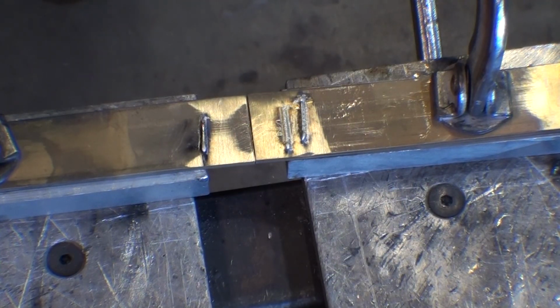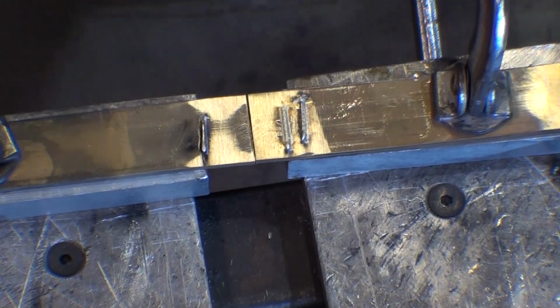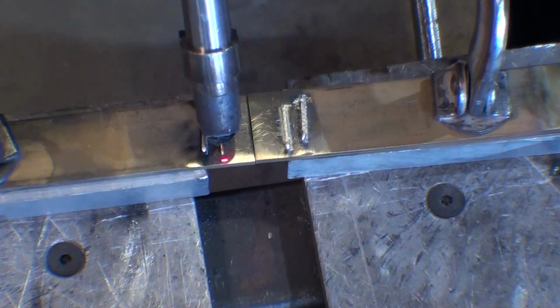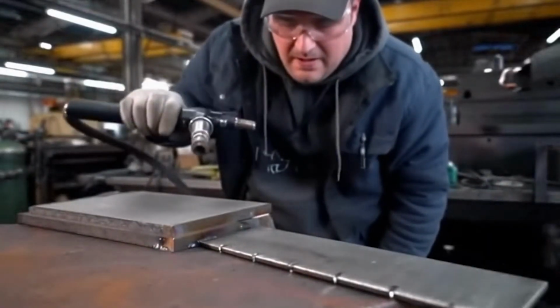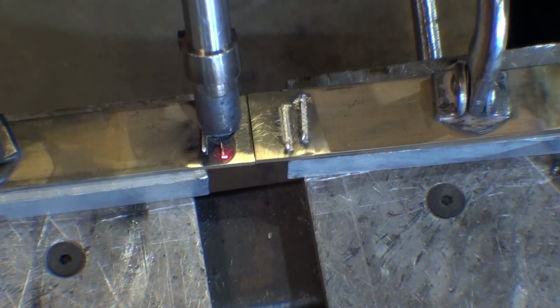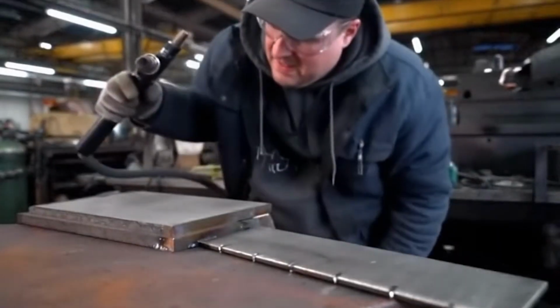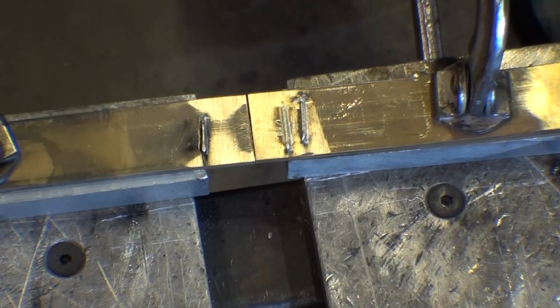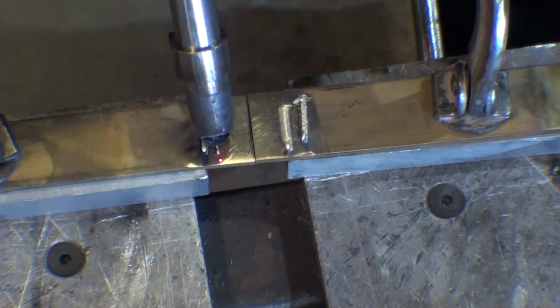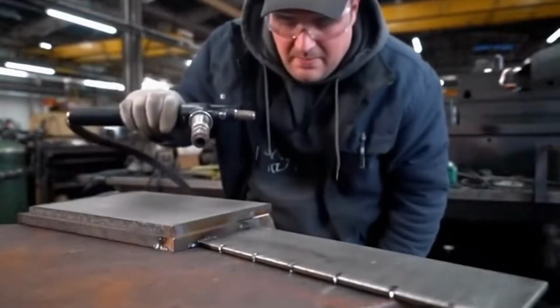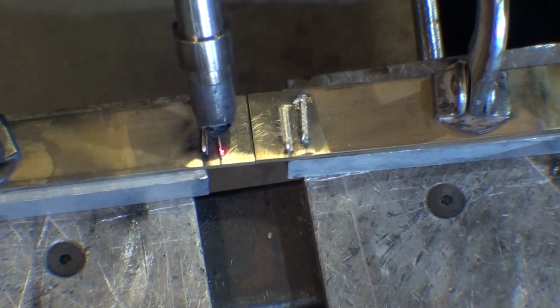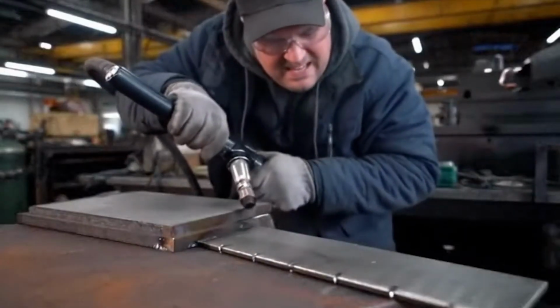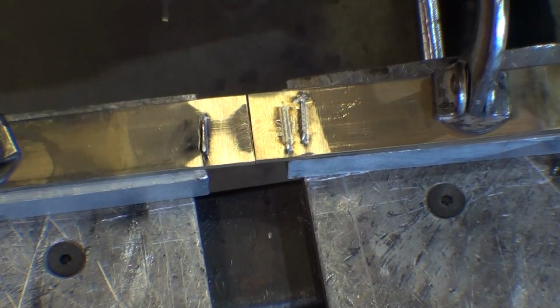Base composition: 92 to 95% copper, 2 to 3% silicon. Trace elements: zinc, tin, manganese, iron. Melting range: 850 degrees Celsius to 890 degrees Celsius is the typical melting interval. The presence of silicon lowers the melting point compared to pure copper, 1085 degrees Celsius, improving castability and fluidity. When used on brass, overheating can cause zinc boil-off from the base metal, leading to porosity and toxic fumes, especially if brass is pushed near its liquidus to 930 degrees Celsius. Silicon bronze melts and flows, but unless the base metal also melts, there's no fusion. That's why it behaves like a band-aid cap on brass, cosmetic, not structural.